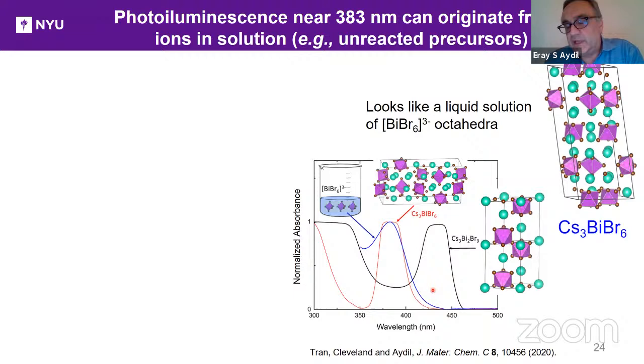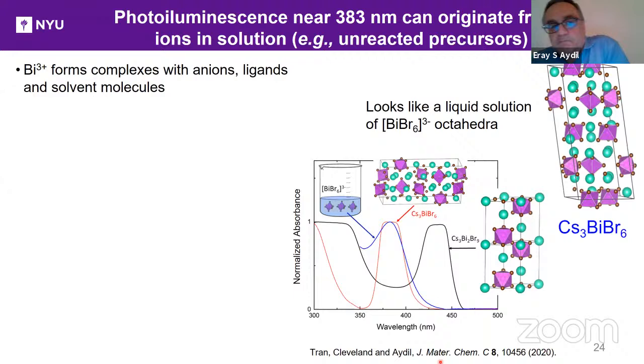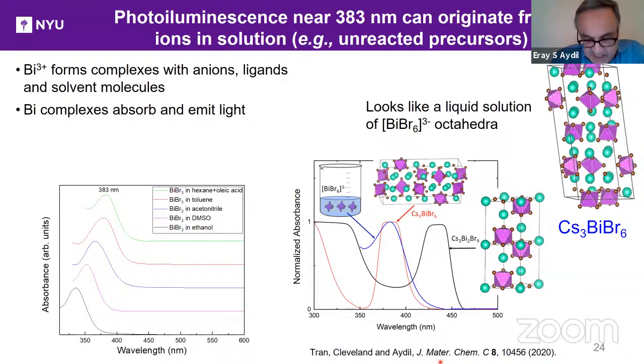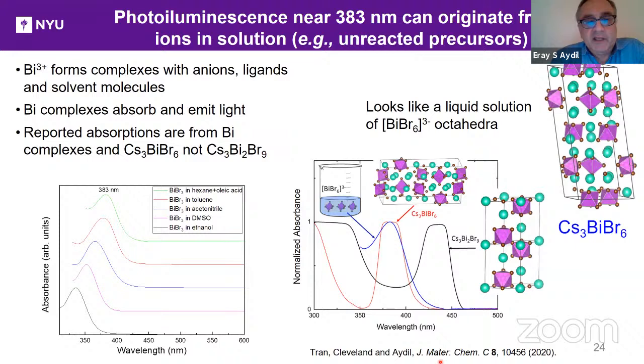When you connect them and they start interacting a little bit, that absorption shifts to 435. Bismuth ions form complexes with anions, bromine for example, and ligands and solvent molecules. And we've been able to obtain optical absorption spectra in various solvents that look a lot like what has been reported for cesium-3 Bi2 Br9. So we think that the reported absorptions are from bismuth complexes and from the impurity phase, monoclinic phase, cesium-3 Bi Br6, and not from the trigonal cesium-3 Bi2 Br9.